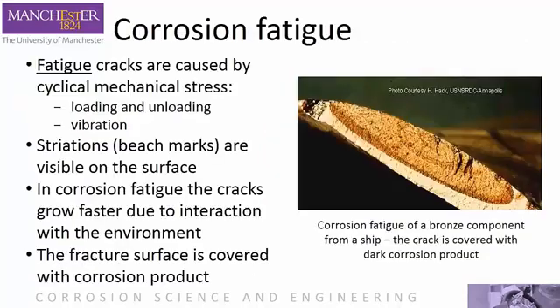Metal fatigue is caused by repeated cyclic stresses that result in the slow growth of cracks, eventually leading to component failure. Fatigue cracks grow much faster in a corrosive environment, and this process is known as corrosion fatigue. You can generally tell the two processes apart because in corrosion fatigue, the broken or fractured surface is covered with corrosion product. Here, part of a ship's propeller has broken off due to corrosion fatigue, and the part of the crack before it broke is covered with dark corrosion product from the bronze copper alloy.